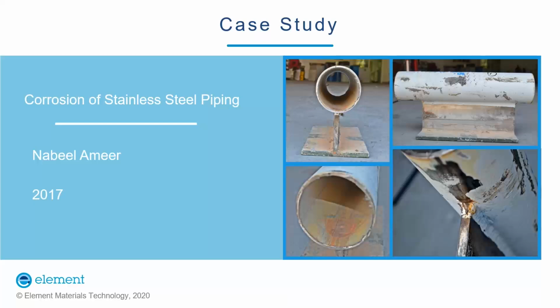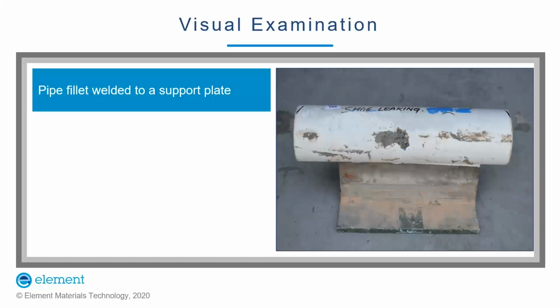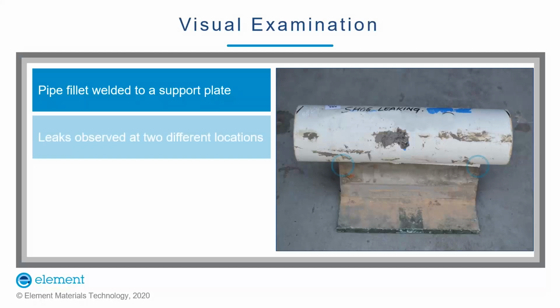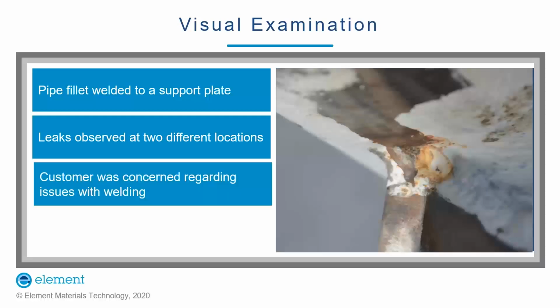After reviewing the background information, the objective of the case study was defined, which was to find the root cause of leakage in the piping system and to check if improper welding or manufacturing defects were playing any role in the leakage. Our investigation started with a visual examination of the pipe we received from the customer. The pipe was found to be fillet welded with a support plate and was painted on the outside. Leaks were observed at 2 different locations in the pipe at the fillet welds, highlighted with the blue circles. This was a concern for our customer as the installation of the piping was completed and called into question if the welds were the cause of the leaks.